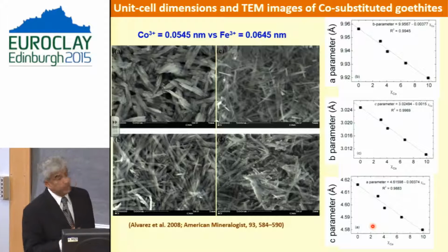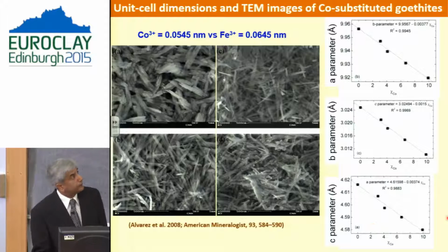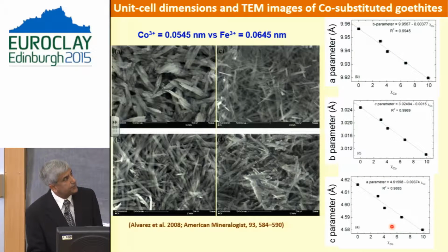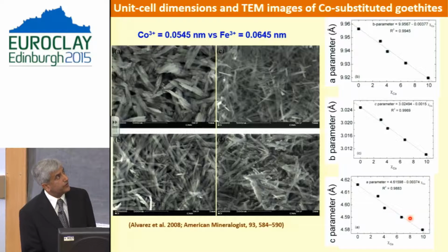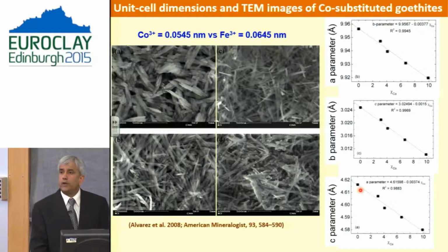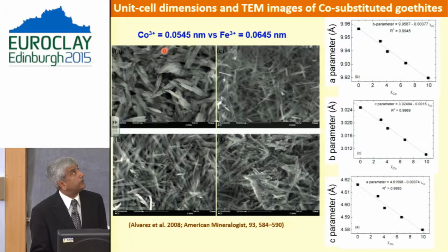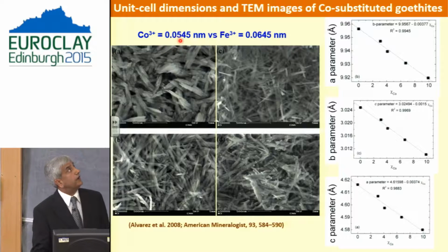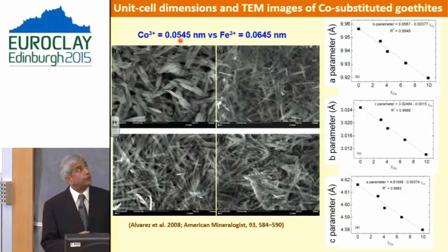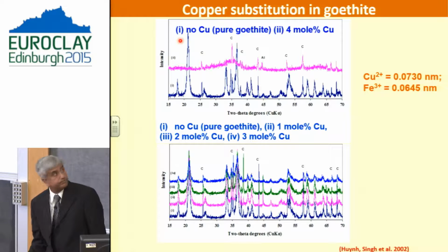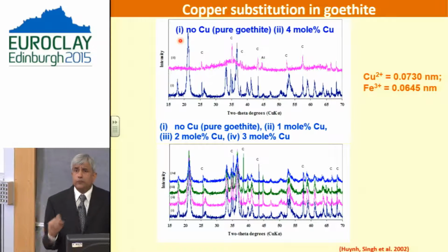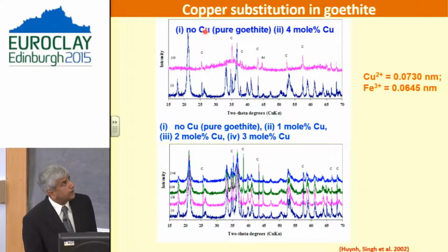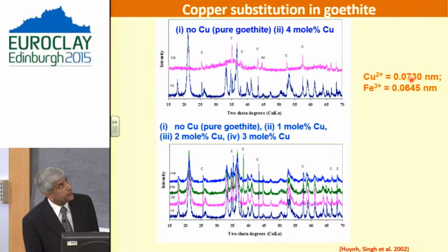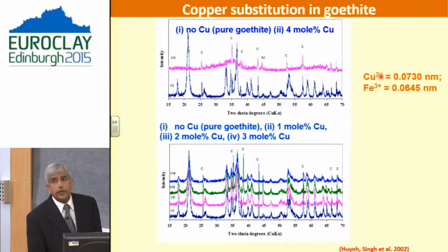Similarly, in case of cobalt, for the limited number of samples, you can see all the unit cell parameters decrease as a result of the substitution of smaller size cobalt for ferric iron. If you look at the copper, which has a slightly bigger size, and it's divalent compared to ferric.